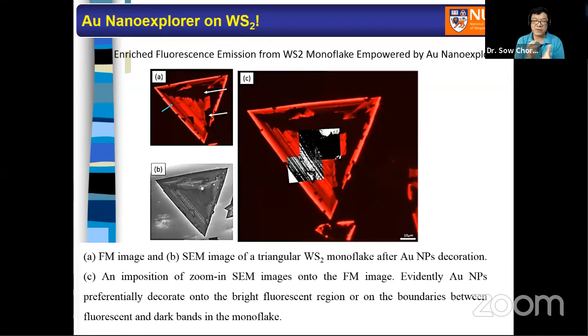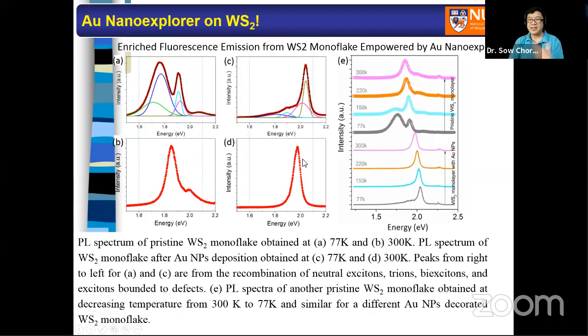The gold nanoparticles seem to be able to find where the exciting regions are, and they decorate onto those regions. The gold decorated regions coincide with the fluorescence pattern. This is very exciting. It turns out that the spectrum also becomes clean. The fluorescence spectrum of the pristine sample shows neutral exciton plus defect bound exciton. But once the gold comes onto it, the gold patches up the defects, suppressing the biexciton, the trion, and the defect bound exciton, and only enhancing the neutral exciton. So this is a way to purify your spectrum, if you like.